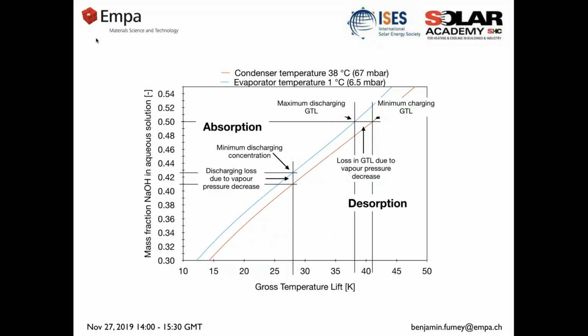When we look at the vapor pressure equilibrium lines stated based on the temperatures that we define, we see here that because in the charging we have a higher condensation temperature than in the discharging evaporator temperature, we of course have gross temperature loss just due to the specific application. And also, more importantly, what we see here is that in the discharging, because of the low vapor pressure, we cannot discharge to the same final mass fraction as would be possible with higher evaporating temperature. So just pointing to the fact that it's very important to have a common basis on the temperatures that we work with.